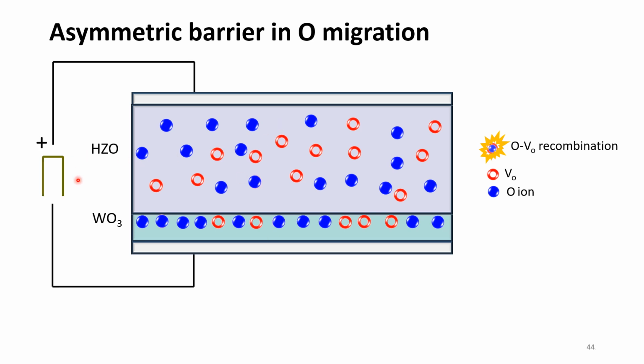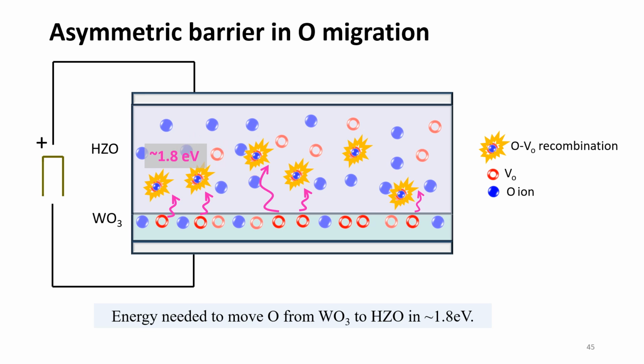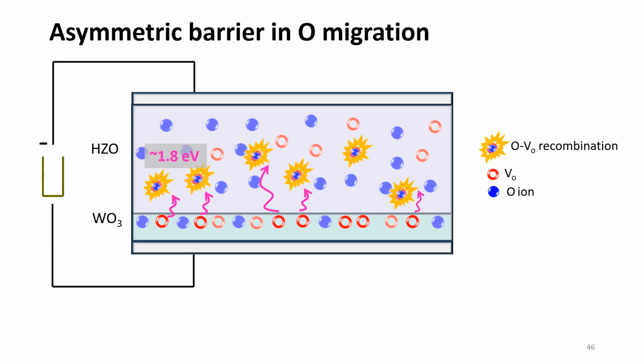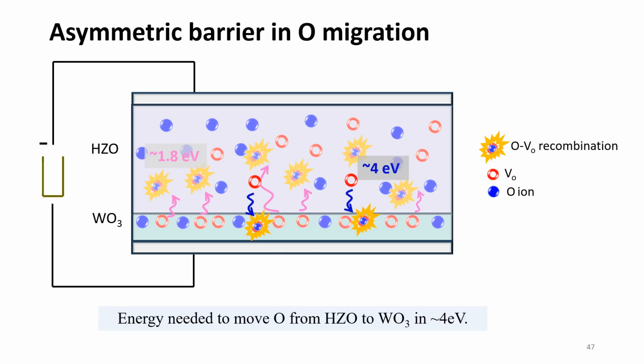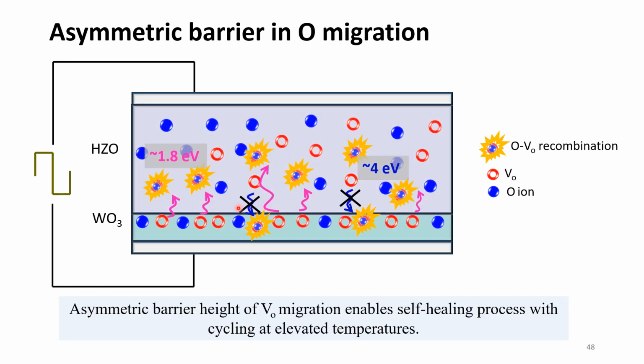When we are applying positive voltage during bipolar cycling, the oxygen from tungsten oxide would want to go to HZO. Say this oxygen wants to go to HZO and recombine. If it does that, it will need an energy of 1.8 electron volt. But during the negative voltage application during the cycling, the oxygen would want to go back to tungsten oxide from HZO and recombine, for which it will need energy of 4 electron volts. So here we can clearly see that it's easier for oxygen to go from tungsten oxide to HZO, and due to the higher barrier height, it's unlikely for oxygen to come back to tungsten oxide.